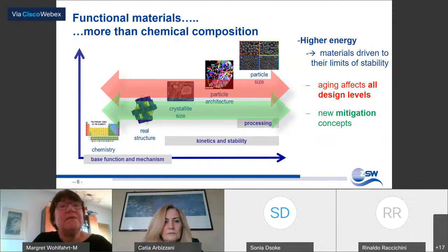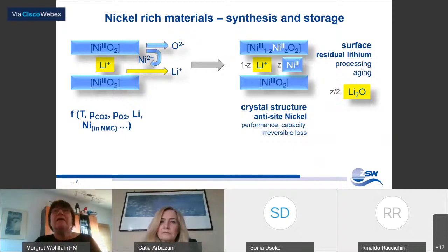Battery materials, this is more than only a chemical composition. To get high energy density, good rate capability, and stability, these materials have to be optimized along the whole chain, from the chemical composition up to particle size distribution, particle architecture, and also the processing to electrodes to get electrodes with high porosity but also high density is very important, and this is a topic for materials development. So let's have a look on the different cathode material.